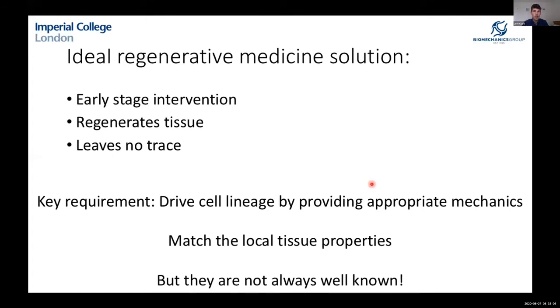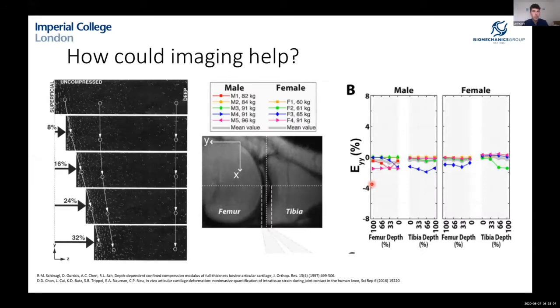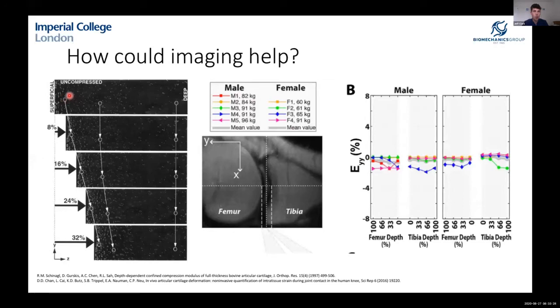So where does imaging come into this? In the past, people have used 2D techniques such as digital image correlation — looking at a slice of cartilage, similar to histology but slightly thicker, and using microscopy to take images as compression is applied. This allows tracking of cell and tissue compression to figure out mechanical properties.